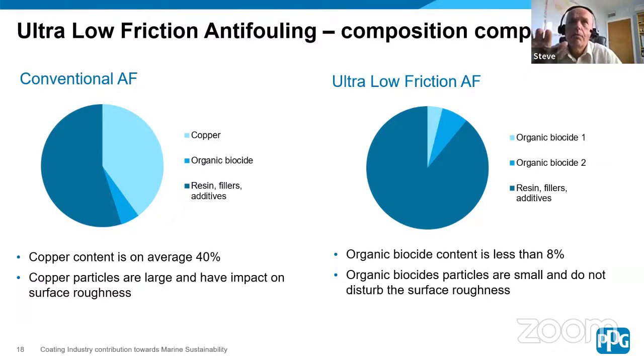And that comes with other added benefits as well. If we think of cuprous oxide, to use your imagination, as a particle, it's granular, it's like a fist shape. So if you have a lot of cuprous oxide in a film, you can imagine the way the particles pack. So you create a roughness. By not having cuprous oxide in there, with particles which are much smoother and flatter, you get a much smoother surface roughness straight away. That's even without the self-polishing, self-smoothing mechanism kicking into place when the vessel goes operational.